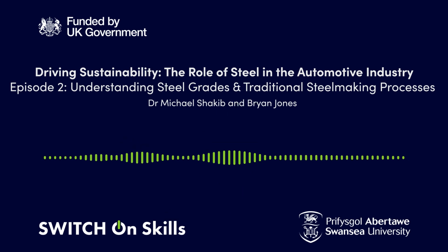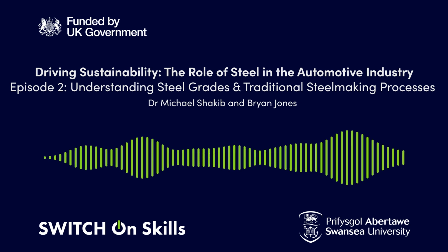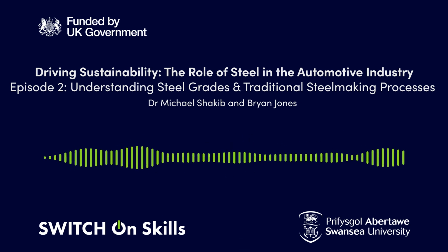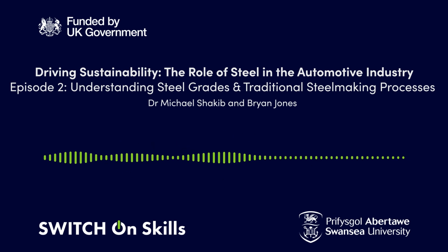Carry on, Bryan. So in the basic oxygen steelmaking process, there's a lot of sulfur present in coal. It's very difficult to avoid having sulfur in coal, and you have to pay a premium if you buy a low sulfur product. So what happens then is that in the first stage, before you pour the hot metal into the BOS vessel, there's a desulfurization stage. In that stage, you reduce the sulfur down to levels which are appropriate for multiple applications of sheet steel products. So following that desulfurization stage, you pour the hot metal into the BOS vessel.